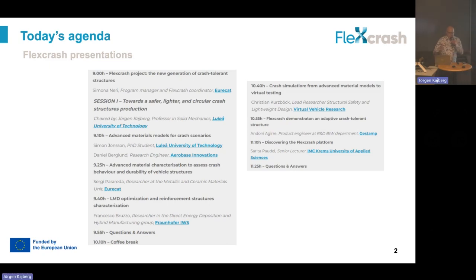Thank you. I think I'll take a question from the chat. It's for Francesco. Are there challenges in the deposition specific to the LMD machine you are using, or are they generally related to the deposition of aluminium? I'm referring in particular to overheating. So the main challenges that I showed today are related more to the deposition of aluminium, where we have this effect of overheating, depositing one layer above the other, and we have to control the parameters for each layer because we have different deposition conditions.